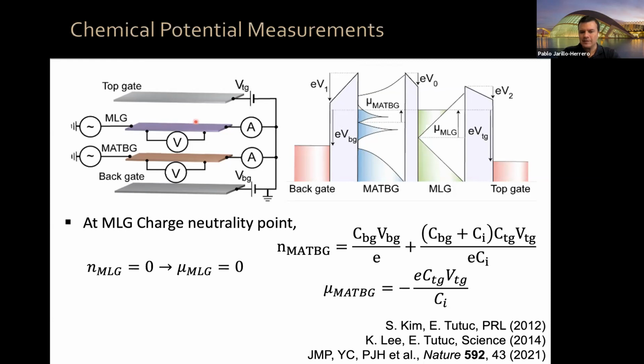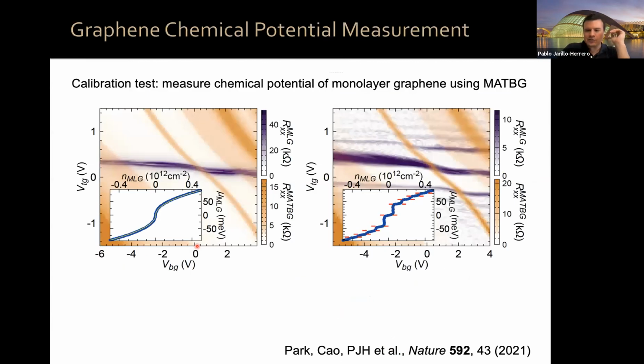And you track that resistivity, then your magic angle bilayer graphene charge density is given by this formula, and the chemical potential of your magic angle bilayer graphene is given by this formula. And again, for the derivation of these equations, you can check there. The fact that the monolayer graphene is at zero at charge neutrality means its density is zero and its chemical potential is zero. So let's do a calibration test.